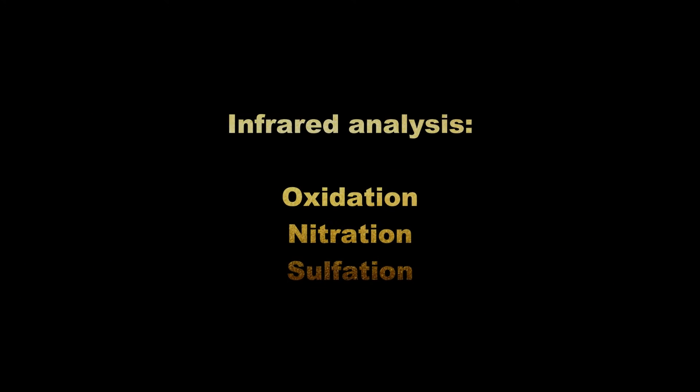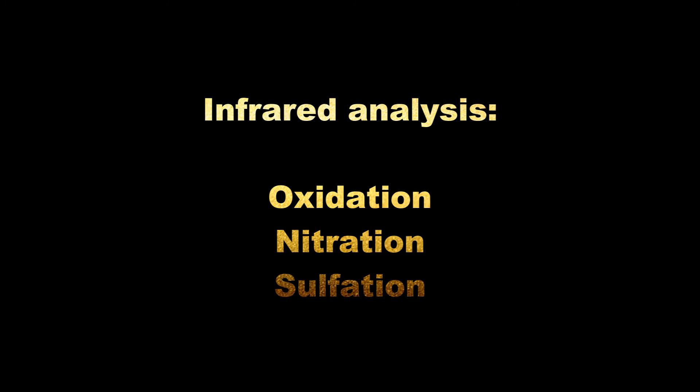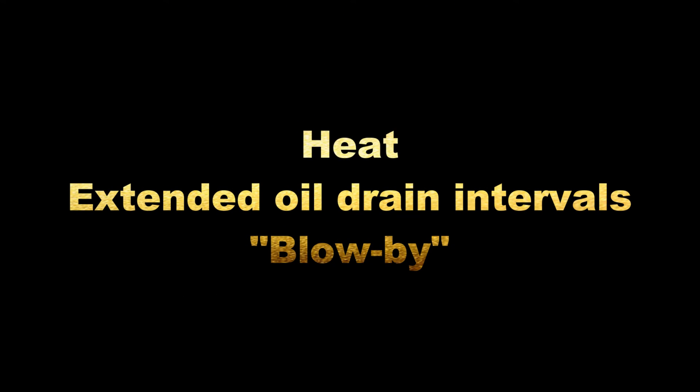Your report may also include infrared analysis to determine the presence of oxidation, nitration, and/or sulfation products. Elevated values are commonly associated with exposure to heat, extended oil drain intervals, or operational issues such as blow-by. Elevated values are commonly seen alongside elevated viscosities and/or soot content.